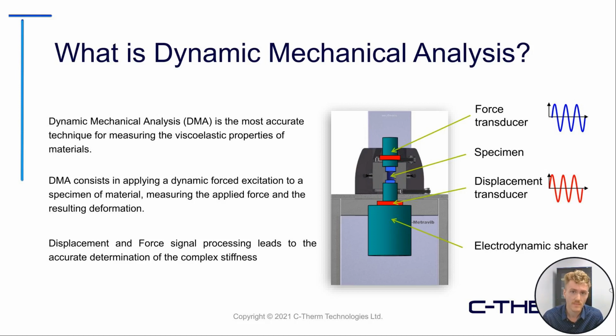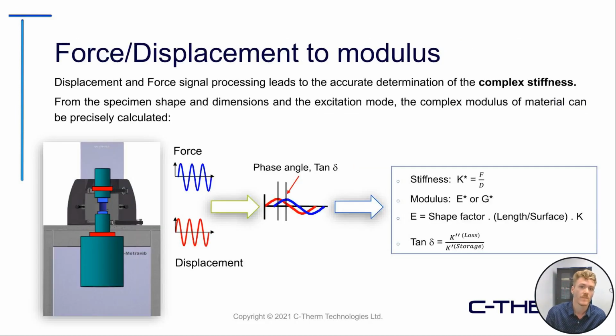DMA, basically the way it works is that we have a sample that's pinned between a force transducer and a displacement transducer. Upon a dynamic excitation or cyclical excitation of a specimen, usually performed by an electrodynamic shaker, we can measure the force and the displacement of these samples. Through displacement and force measurement, we can get an accurate determination of the complex stiffness of a material itself. So the stiffness or the complex stiffness is given by the force over displacement.